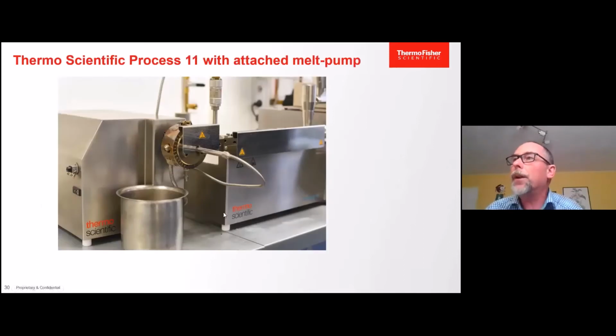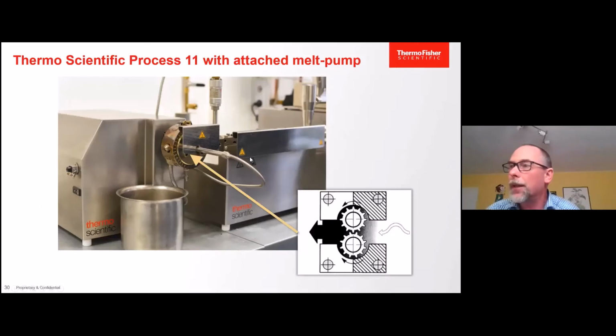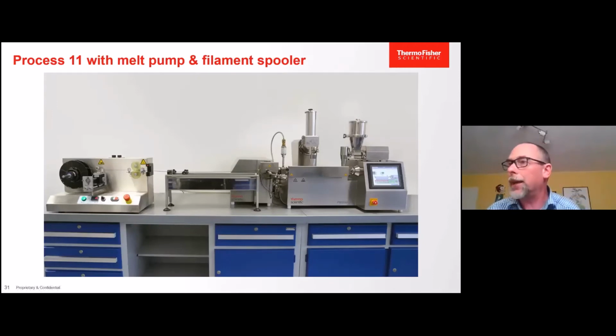In this process, we now introduce a very small scale melt pump. The melt pump is attached to the extruder. A melt pump, also called a gear pump, is a heated component with two gears. They take the melt and process the melt through those gears. They compress the melt, they boost the pressure, and by the many teeth in those gears, they make a more equal pressure behavior. So they equalize the pressure coming from the twin screw extruder and create an even pressure profile at the die tip over here. And all this line can be a small tabletop line, as in this case.